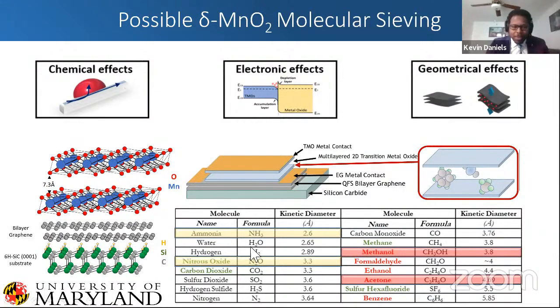We exposed it to ammonia and NO2. If you look here, the kinetic diameter of those are actually much smaller than the 7.3 angstrom interlayer spacing here. Now, methane and then isopropanol is actually a little bit higher than acetone. It's like 4.8 kinetic diameter. Those are actually being screened. And so this is one reason we think that the selectivity side of things is definitely being caused most likely by this screening effect of the interlayer spacing in the material as shown here.